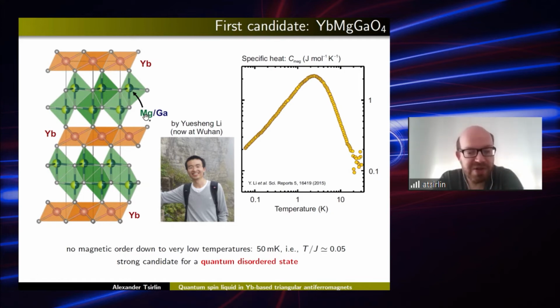Well, how do we know that this material has a potential to show the spin liquid behavior, that this material is different from any other antiferromagnet? First of all, we measure specific heat because specific heat is a good probe of possible phase transitions. Here you see the specific heat measured down to 50 millikelvin, and you see that there is a broad hump, but no anomalies, which means that there should be no magnetic long-range order. Indeed, this material is a strong candidate for the quantum disordered state because this temperature of 50 millikelvin is about 5% of the exchange coupling. So indeed, all over this range, the spins should be correlated, but should not develop any long-range magnetic order.